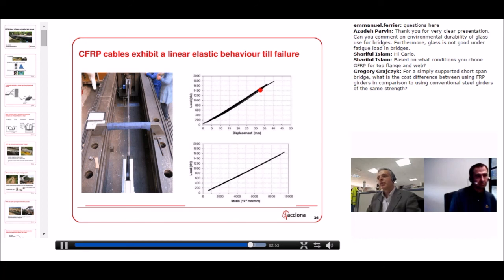You see, the failure is actually explosive, and what we did, during the installation we installed strain gauges on, if I remember, 8 of the cables, and we checked the evolution of the strain of the cables during the installation process and in service. This is how we manage these cables. And one of the concerns was mainly the creep of the cables, but so far we haven't observed much creep in these cables.